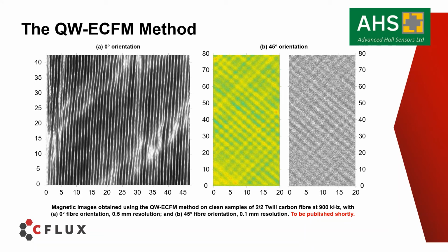In this case, the contact points between warp and weft fibres were detected, which appear as the yellow, stronger magnetic field responses, where in a small, localized spot a linear region of eddy current is still able to be formed and hence detected. At other points on the sample, where there is no electrical contact between fibres, no linear eddy current region can be formed, and hence the detection of weaker, i.e. background, magnetic field in green.